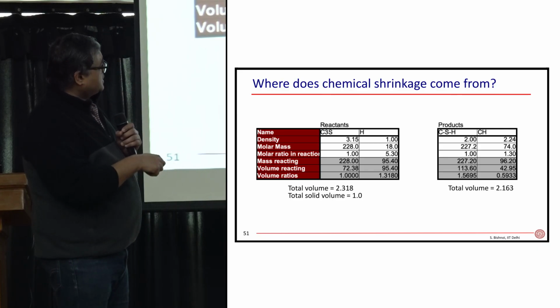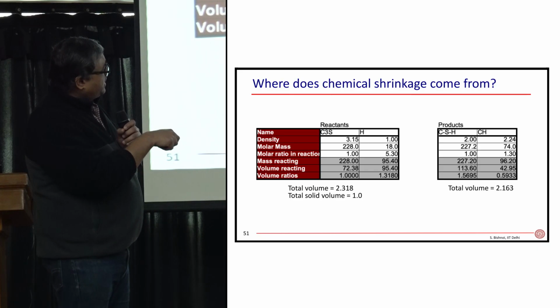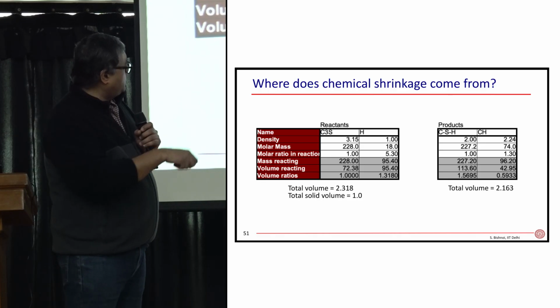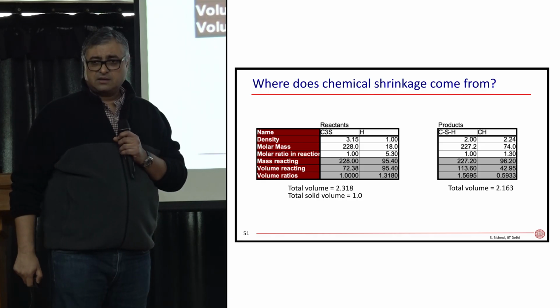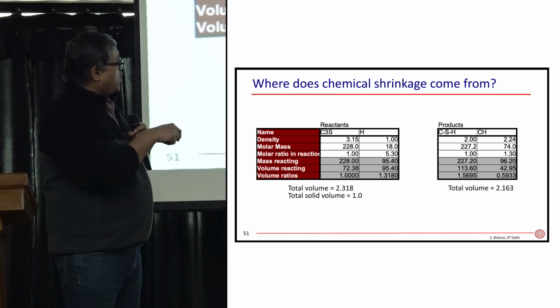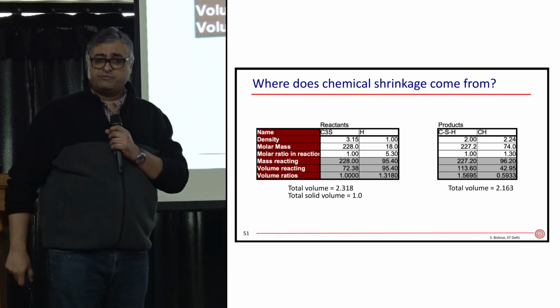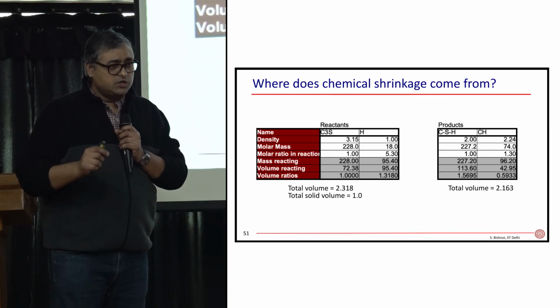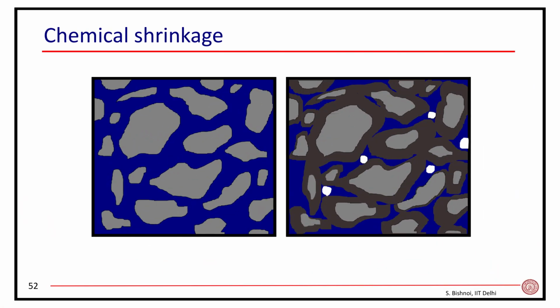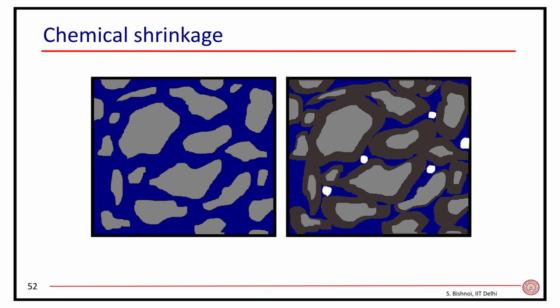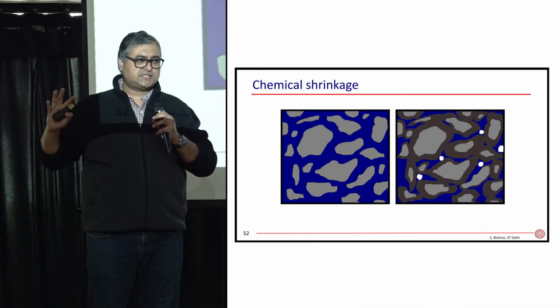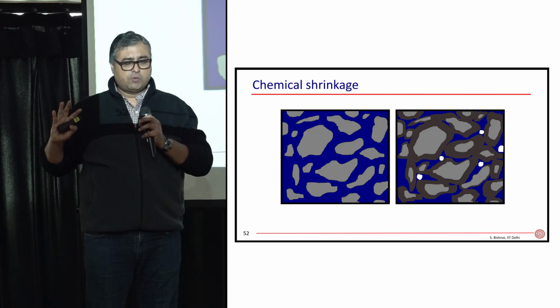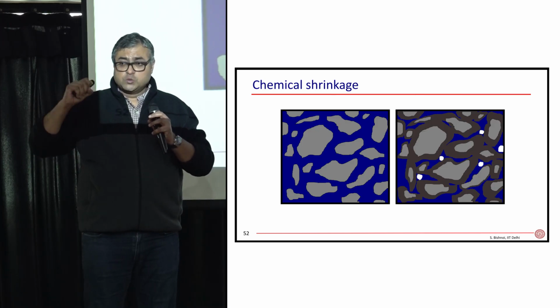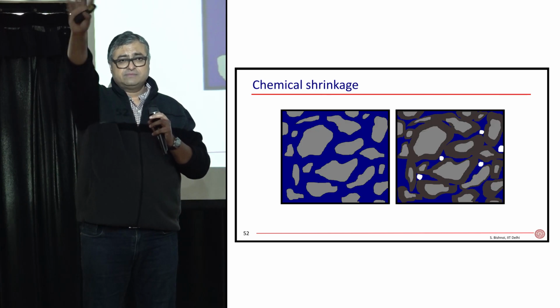The other thing that you would notice is this plus this is 2.318, but this one is 2.16. That means the volume of solid plus liquid is reducing after the reaction. And because the volume of solid plus liquid is reducing after the reaction, you produce voids inside the cement paste. Because now, if the cement paste has set, the size of the box in which the cement paste is cast is set.